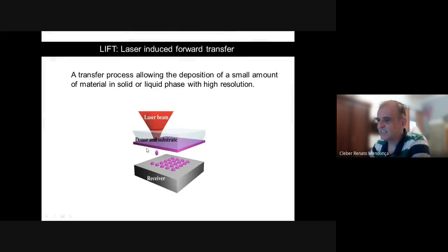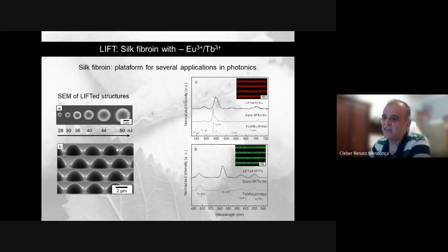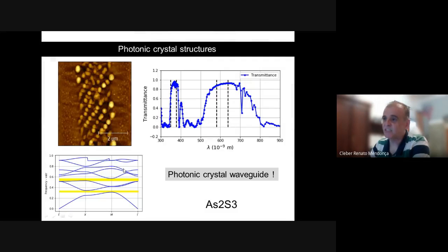So you can get structures which are somehow like cavities emitting light in the green or in the red, depending on if it's doped with europium or terbium. So that's something we are able to do. Something else we are doing is fabricating photonic crystal structures. In this case, by using LIFT in chalcogenide glass, arsenic trisulfide, we are able to fabricate those structures. As you can see here, every part of the structure is about 150 nanometers, and the idea is to create a quasi-periodic structure that can act as photonic crystals.